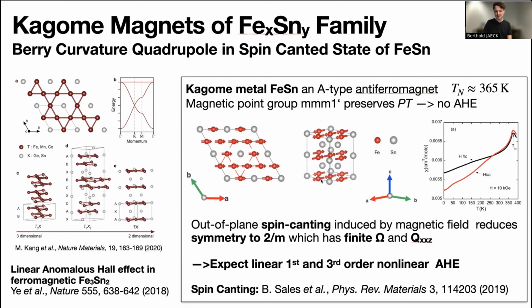However, what is interesting is that if you slightly reduce the magnetic symmetry of the system, for example by canting the spins out of plane, you lower the symmetry to 2/m, which has a finite Berry curvature and Berry curvature quadrupole. What is interesting is that this out-of-plane canting of the spins has been observed previously by a group at Oak Ridge National Lab when you put this compound in a large enough magnetic field.